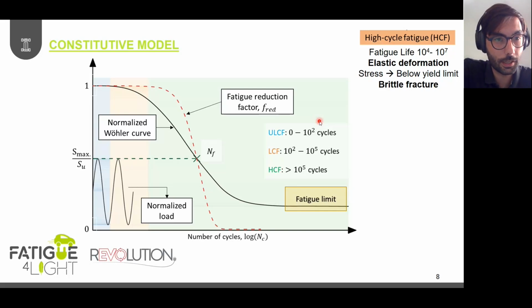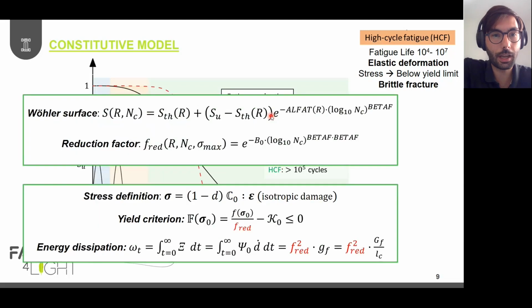And this Wöhler curve, which is the black line in the figure that we can see in this slide, relates a level of stress during the cyclic loading with the maximum number of cycles that the material would be able to withstand without starting to crack or developing degradation. Okay. In this case, to model this effect, we introduced in our model the so-called fatigue reduction factor, this f_red, which is represented by the red dashed line. And in the next slide, we will see how it is computed and accounted for in the model. Well, I'm not going to get into many details, but based on this Wöhler curve, we can compute a fatigue reduction factor, this f_red, which will depend on several material parameters that can be estimated with experiments, and obviously on the number of cycles, n sub c in this case.